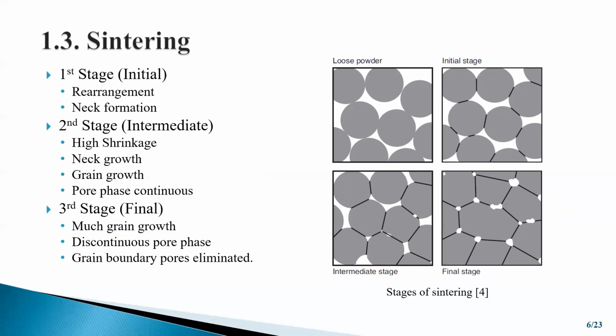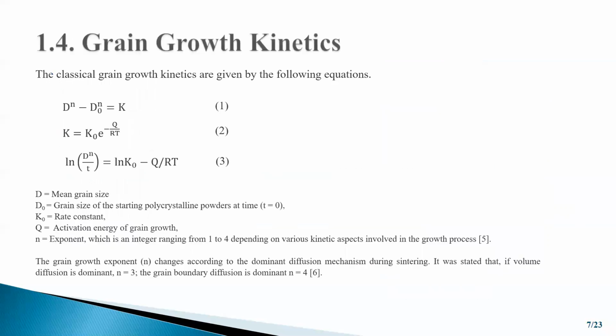The third stage of sintering is called final sintering. It involves the final removal of porosity. The classical grain growth kinetics are given by the following equations. The exponent n in equation 1 changes according to the dominant diffusion mechanism during sintering. It was stated that if volume diffusion is dominant, n equals 3, and if grain boundary diffusion is dominant, n equals 4. In our study, we tried to estimate this n value for our powders.